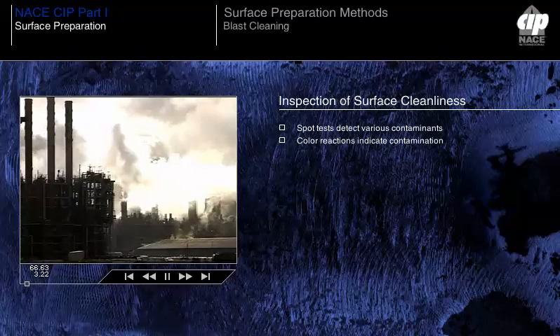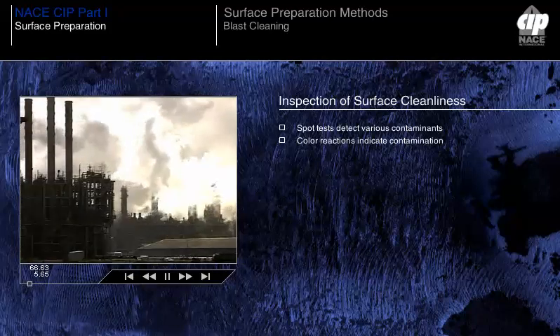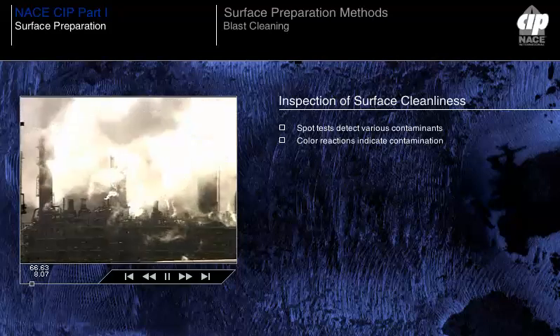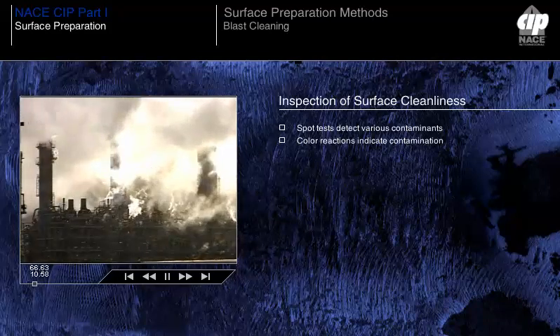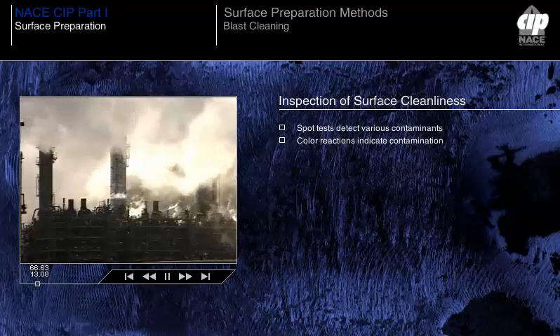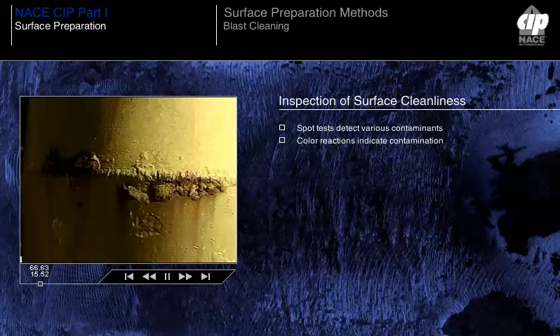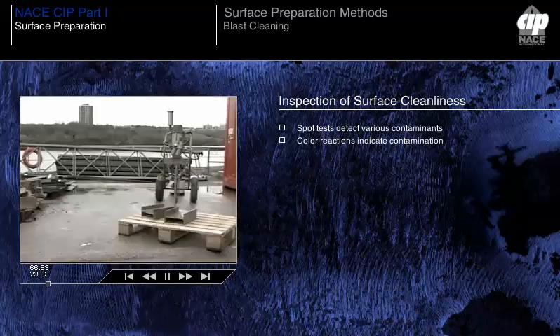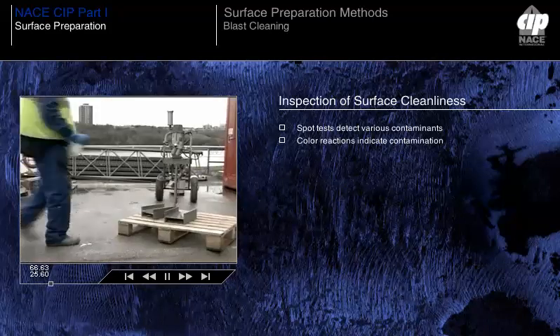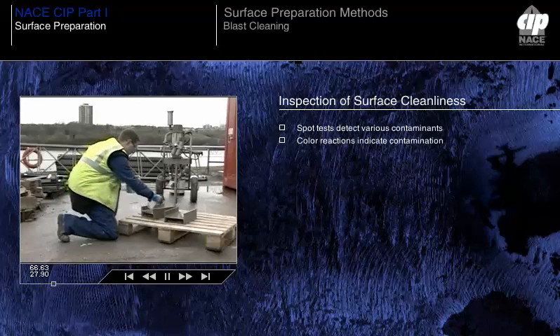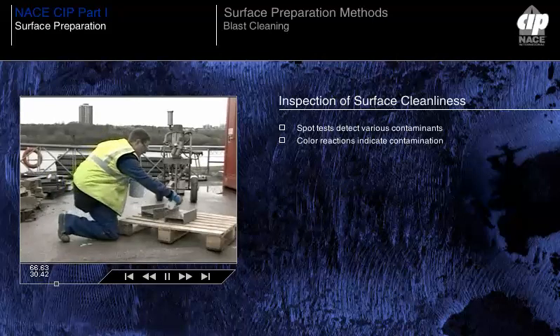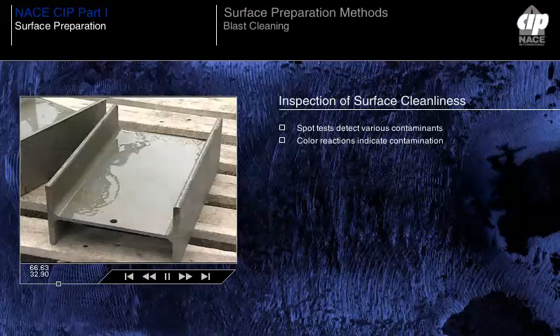The rust which forms on steel surfaces exposed to either industrial or marine atmospheres may contain significant quantities of sulfates and chlorides. If these compounds are not removed, they can give rise to premature paint failure. Spot tests have been developed to detect the presence of soluble iron, sulfates and chlorides on blast-cleaned steel. In these spot tests, color reactions are used to indicate the sites of contaminated rust.